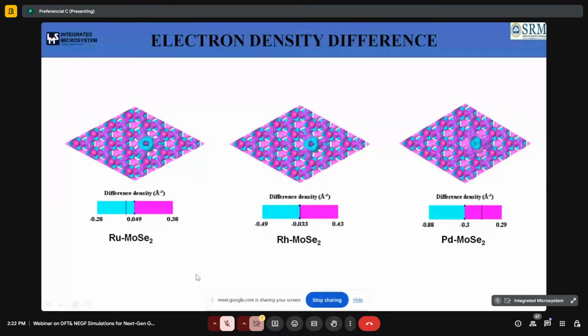If you look at the dopant region, we can observe only the depletion and not the accumulation. The accumulation has not happened, only the depletion is happening around the dopant, which validates that the dopant acts as a donor and the system acts as an acceptor. Right, so a proper charge transfer has happened, which means the dopant is strongly interacting with our system, that it is strongly doped with our system, and that can be confirmed.